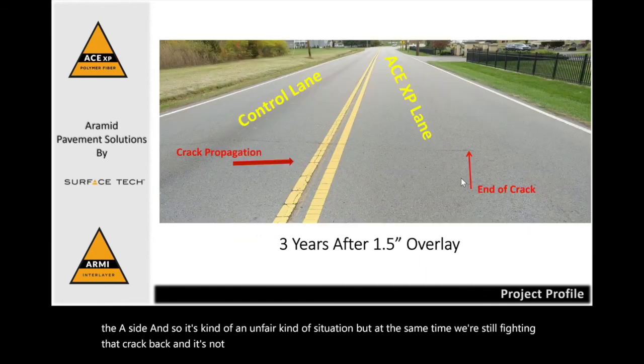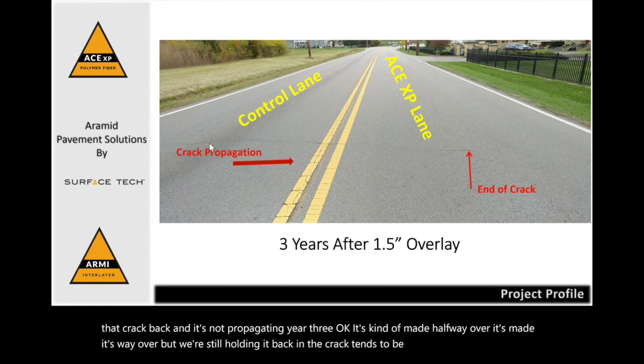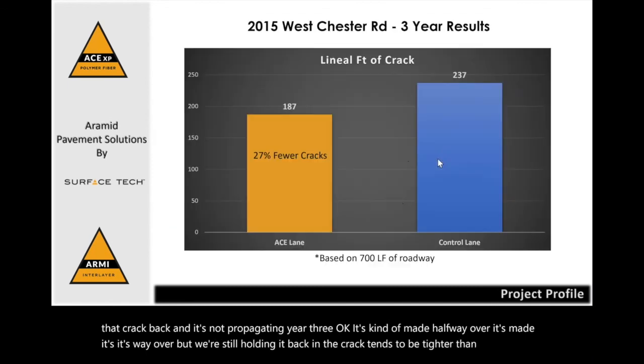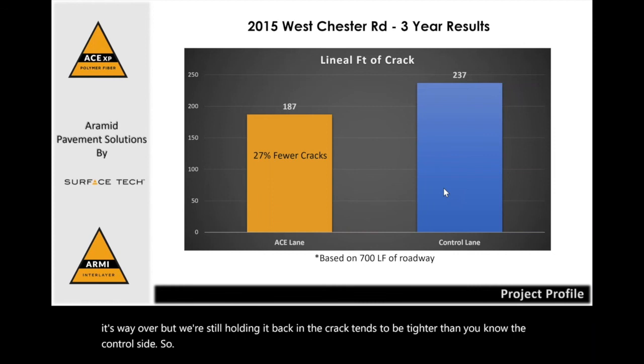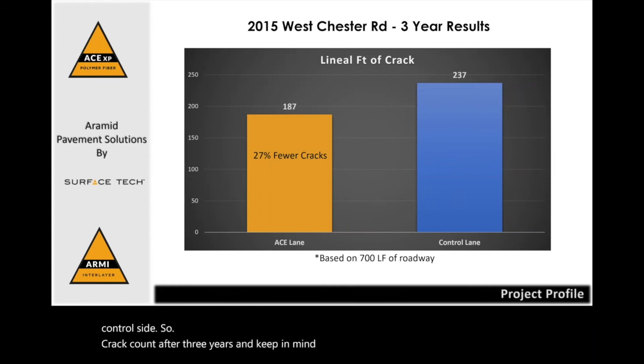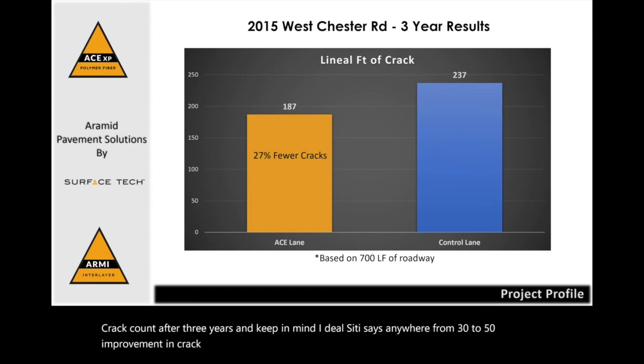Year three, okay, it's kind of made halfway over. It's made its way over, but we're still holding it back. And the crack tends to be tighter than the control side. So crack count after 3 years, and keep in mind, ideal CT says anywhere from 30 to 50% improvement in crack mitigation. Well, in that first year, we were 100%. By year three, we're down to 27%.